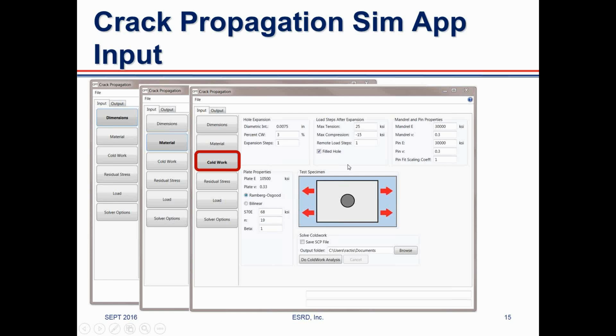One of the requirements that was important for this project was to recognize that when holes are cold worked, they're typically filled with a fastener. And if some overload events occur during the life of the part, this overload and underload, that means positive or negative in terms of tension or compression, can change the residual stress field. With this module, what we accomplish is the ability to give the analyst the possibility of testing those hypotheses. If they detect that there is an overload or underload event important in the operation, they can recompute the residual stress distribution due to those.